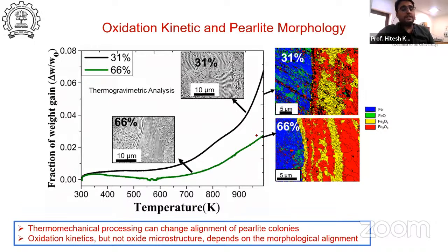So we did the EBSD analysis of the oxide which is forming. What we observed is that when the material is less aligned, 31% aligned, we are getting some cracks in the oxide scale. Why are these cracks forming? The cracks basically mean the oxide scale which is forming is not very adhesive to the substrate, and these cracks provide a path for oxygen to interact with more substrate and form more oxide scale. That is one of the reasons why it is happening. But in the case of 66%, there are some porosities, but not as many in comparison to 31%. So this is clearly visible. We can comment that this alignment is changing the oxide morphology only, not the oxide phases. This is basically the morphology of the oxide scale.